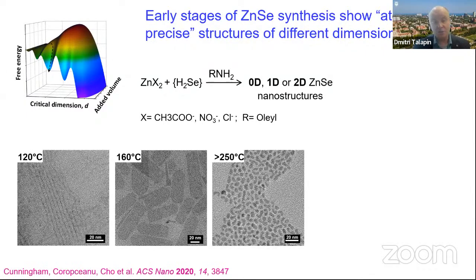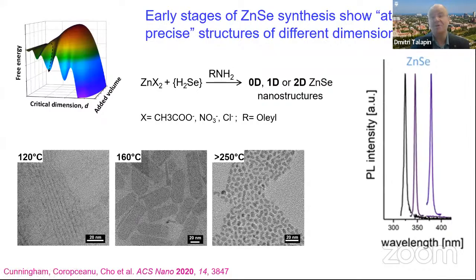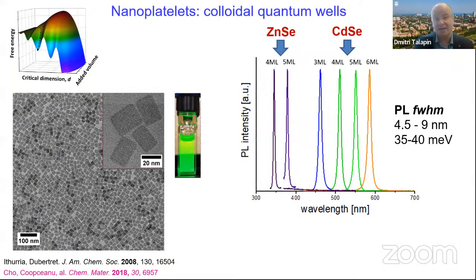This can be demonstrated by fine-tuned solution synthesis of different systems. For example, you can start with a zinc precursor and a selenium precursor and react them, and depending on temperature, this system can navigate different pathways along this free energy surface. The same material with a cubic unit cell will form one-dimensional atomically precise wires, two-dimensional platelets with atomically precise thickness, or three-dimensional structures. That has been best optimized to date for finding these valleys leading to two-dimensional structures that have the electronic structure of quantum wells. So they're colloidal quantum wells, but they have true atomic precision along the thickness. And it's chemistry, so it's solution synthesis. You can make grams, kilograms, you can scale it. So these can easily go into commodity materials.